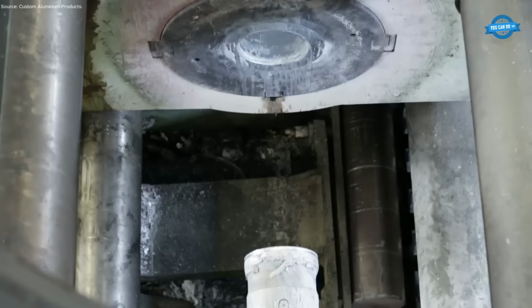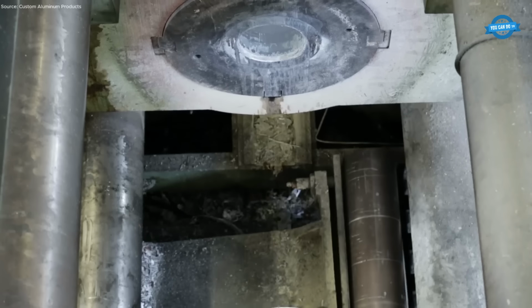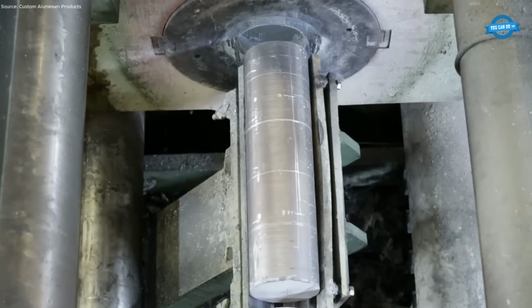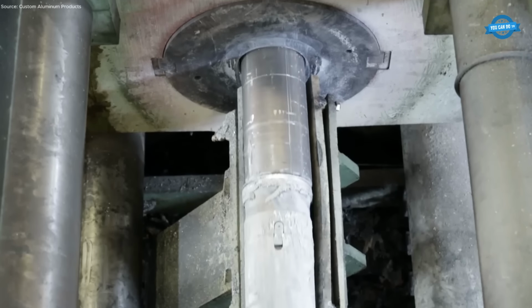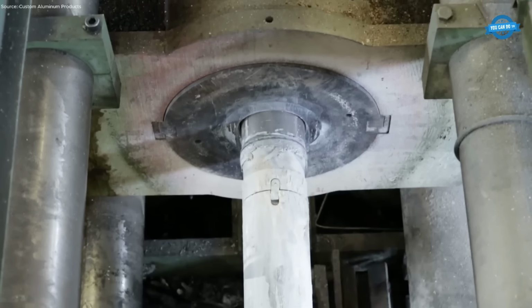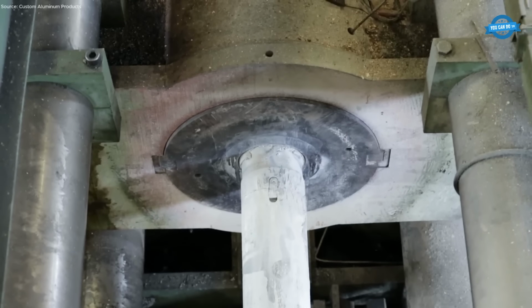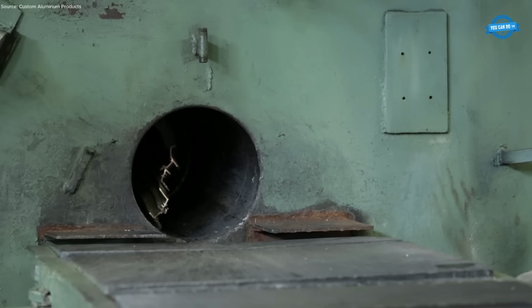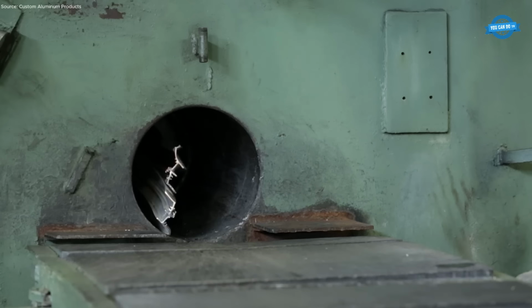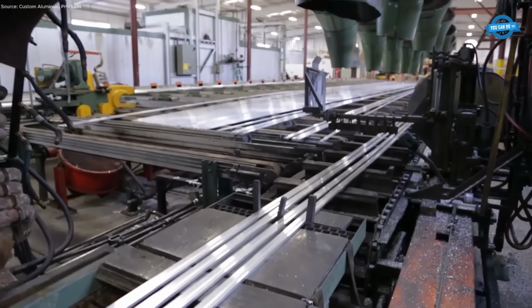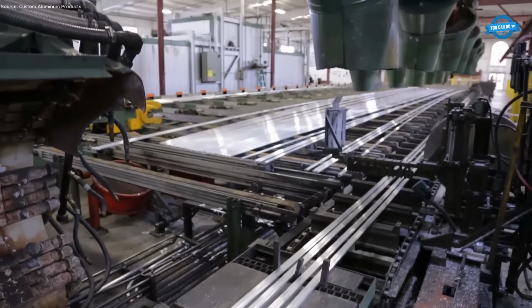Once heated, the billet is sheared to an optimal 30-inch section, tailored for the profile to be produced. The extrusion loader positions it into the press, where a hydraulic ram unleashes up to 3,000 tons of pressure, driving the billet into a hardened H13 steel die. The metal flows through the die's precise openings, emerging as a continuous profile with exacting cross-sectional detail.